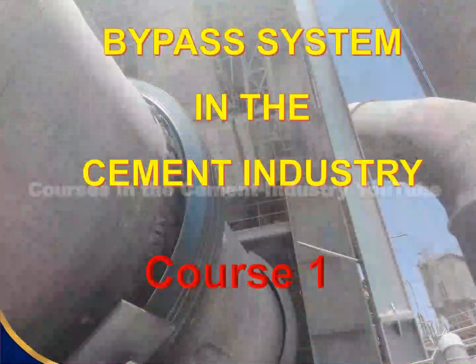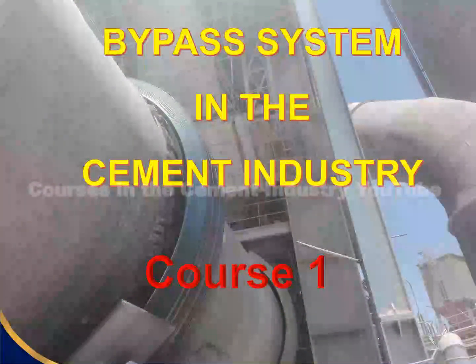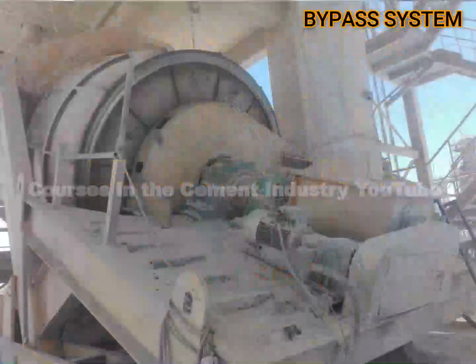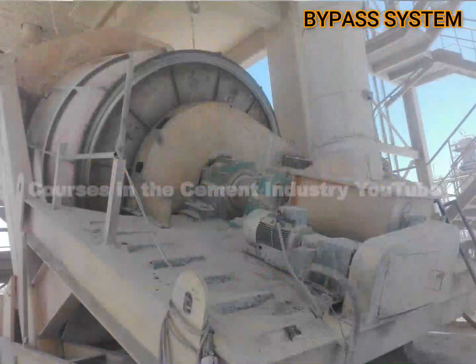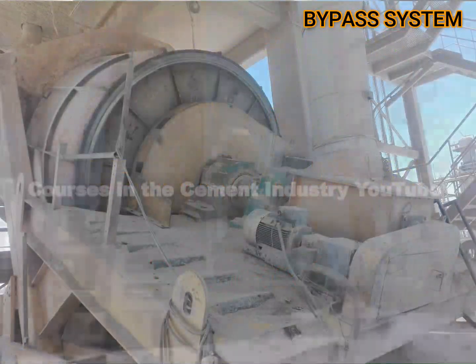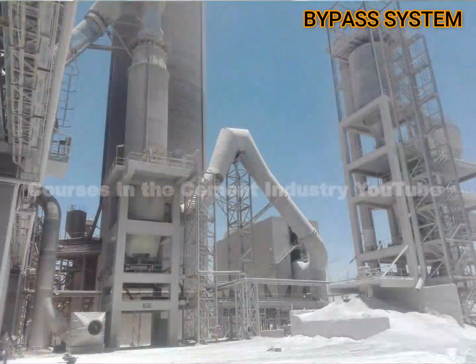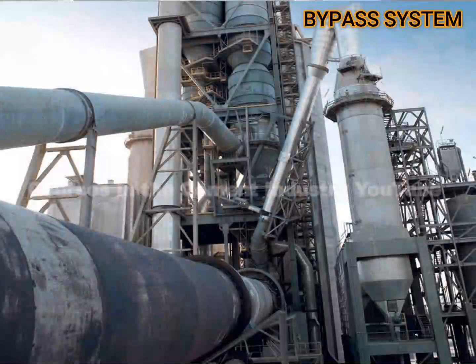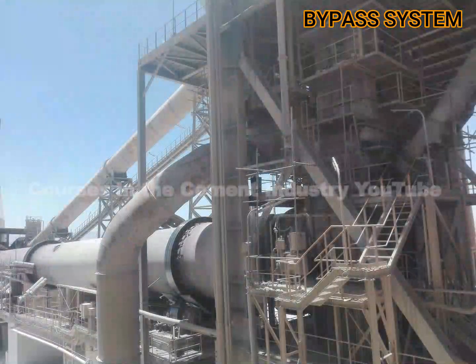Course 1. A bypass creates a valve for circulating elements in the rotary kiln and removes elements such as chlorine, sulfur, and alkalis until the coating or clogging situation in the preheater and rotary kiln becomes controllable with the help of cleaning. A bypass is used for the removal of alkalis in case low alkali cement is being produced.